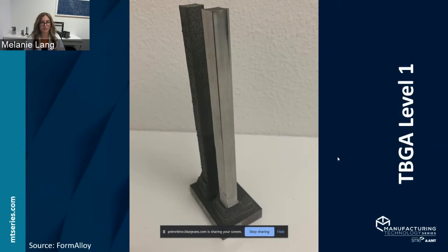I wanted to show this example because there can be some challenges with working with H13 and tool steel in particular with respect to preheat. So there are definitely considerations to take into account with your tooling and the geometry and the material. In our case, we do automated preheat with an induction heater. We can automate the process to put the tool in there, scan it to understand what needs to be repaired, and then have an induction heater come down, heat it up to the desired temperature within seconds, and then immediately begin deposition. And you're able to get a really nice bond and a really nice build that way. So just another simple tool example here that can be made out of H13.